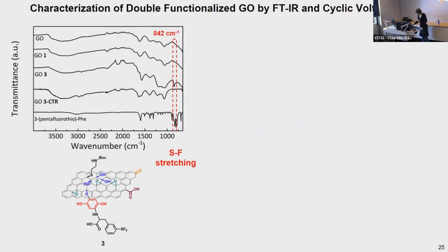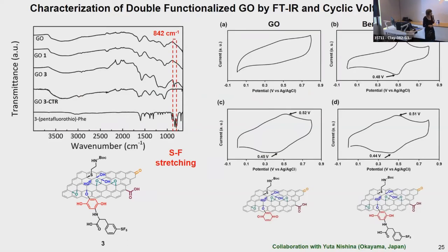And we also exploited the fact that benzoquinone is present on the surface of graphene oxide because it has redox activity. So we used cyclic voltammetry. So this is the profile of graphene oxide with no specific redox activity. This is the profile of benzoquinone with these two characteristic peaks that we also found in this intermediate conjugate and also in the final conjugate, so confirming the presence of benzoquinone on the surface of graphene oxide. So you see that by exploiting different characterization techniques, we were able to confirm the outcome of the two reactions on graphene oxide.